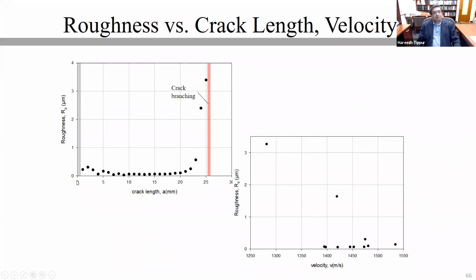The gray line here represents your notch initiated, and then there is some roughness, and then it settles down to a nanoscale surface roughness, which is where the mirror region is. And the mist region is somewhere over here. In the mist region, the surface roughness is still below 1 micron, about half a micron. And then this value very rapidly increases to about 4 or 5 microns when the branching takes place, indicated by this red line.